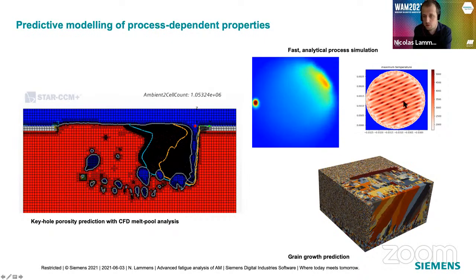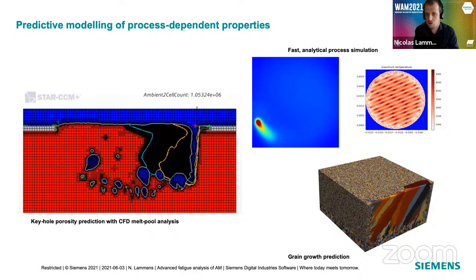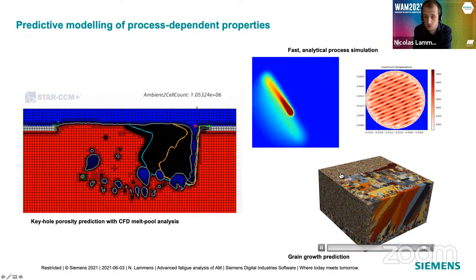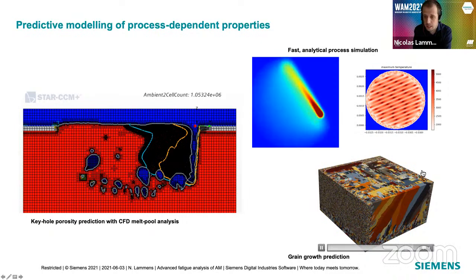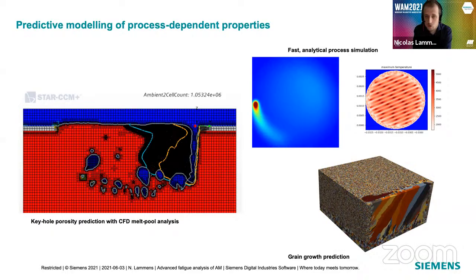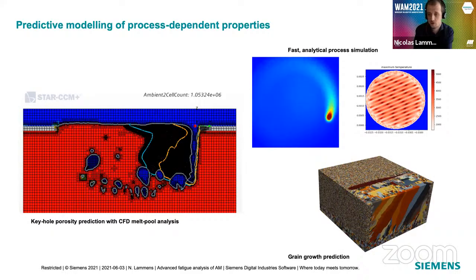And one of those examples you see here at the top is where we try to predict the temperatures that exist during the process, taking into account the laser settings and the scanning strategy. And based on that, we want to predict the temporal evolution of the temperature. And if we have those, we can actually look towards things like grain growth prediction, what you see here at the bottom. And our final goal is to be able to capture everything that happens during the printing process, to know what features you can expect in your component, and then to be able to predict from that the performance of your component.